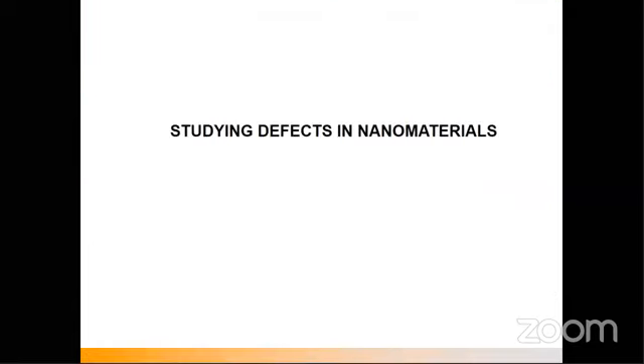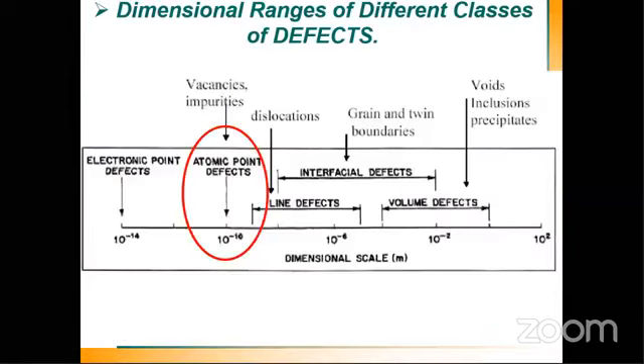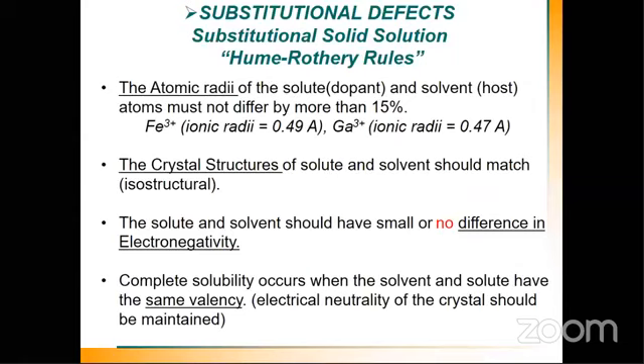Because I'm talking about the dopants, due to time constraints I will just say, for students: when you are selecting a dopant, you have to keep into consideration the Hume-Rothery rule. For example, in a LiFeO2 material, if you want to put gallium in it, it's an ideal dopant because it has ionic radii in a similar range. In iron, the ionic radius is 0.49. In gallium, if you want to use it as a dopant, it is 0.47.